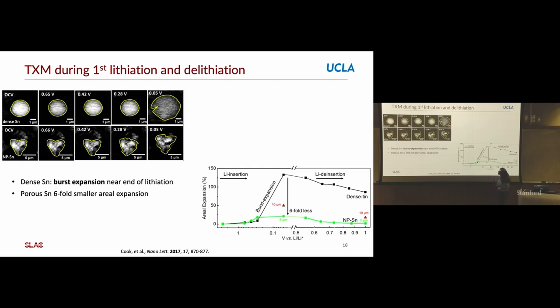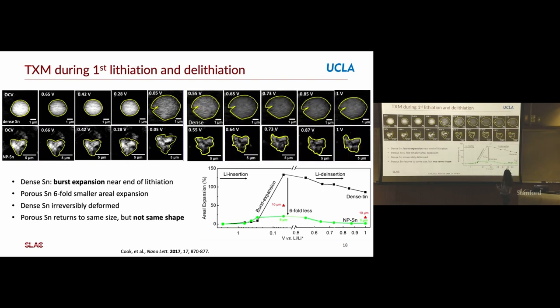You can see the nanoporous tin does not have a very large volume expansion or areal expansion, and it goes back to its original after you delithiate it. Whereas the dense tin had this very burst expansion and then actually just keeps its same area as you take the lithium out. And so there is a large change that's irreversible in the dense tin in that very first cycle that you don't see as a volume or area change in the porous tin, but we are definitely not keeping the morphology the same. So it wasn't a perfect solution. And that's what the X-rays could give us.